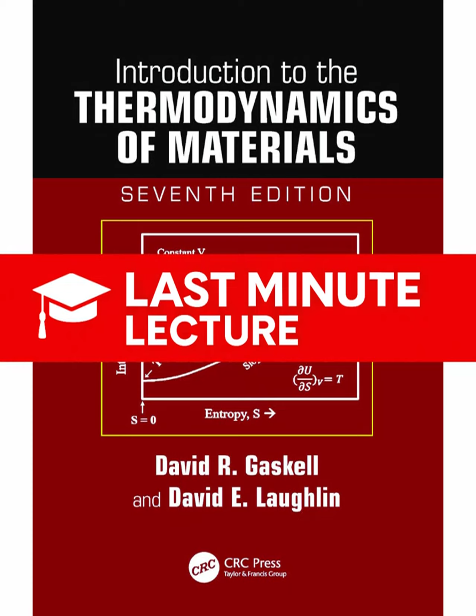That was a fantastic deep dive. So to just quickly synthesize this for you listening. First, stability at constant T and P is all about finding the minimum Gibbs free energy, G. The lowest G always wins. Second, the slopes of your G versus T and G versus P plots are just minus S and V. This means the highest entropy phase is stable at high temperatures.